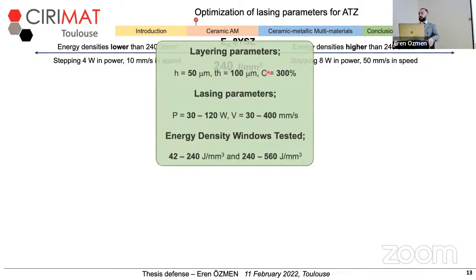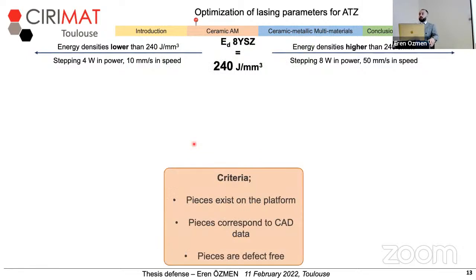And I kept layering parameters stable as well, because they have similar morphologies. And I created 26 different combinations between laser power and lasing speed to try energy density windows lower than 240 and higher than 240. To evaluate the pieces that I fabricated with these windows, I applied 3 different criteria: pieces are existing on the platform, corresponding visually to the CAD data, design data, and pieces are defect-free.